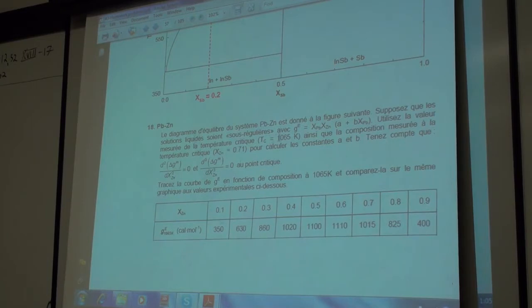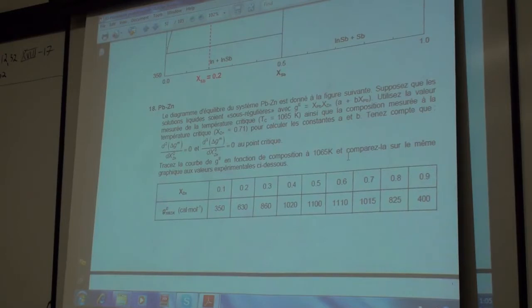Critical temperature was measured at 1065 and the composition was measured at 0.71. So the coordinates of the maximum point are about 1065 and 0.71. And I said, okay, calculate the constants A and B using the fact that the second and third derivatives are zero at the critical point. I hope you realize why that's the case.